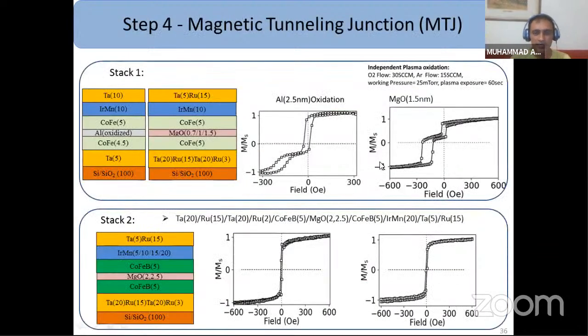Here, step 4, I have also prepared the magnetic tunneling junction, the stack of this with metallic aluminum. Then I oxidized the aluminum under these conditions in our sputtering chamber: oxygen flow was 30 SCCM, argon flow 15. I chose a working pressure of 25 millitorr for growth of the films, and a plasma exposure of 60 seconds.